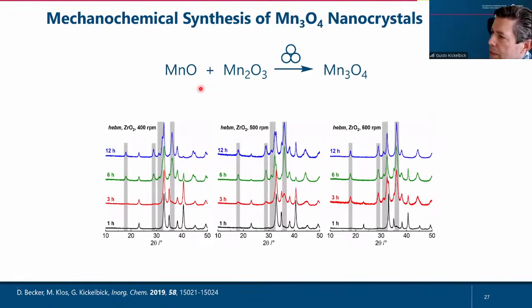So here is another interesting experiment. We wanted to generate manganese oxide with the oxidation states 2 and 3. And this usually, under usual temperature conditions, takes a long time and usually needs to be done under very restrictive conditions concerning the oxygen presence. But in the mill, you just mix manganese 2 and manganese 3, and you get out the final material. After 3 hours, you start to see it, and after 12 hours, the reaction is over.